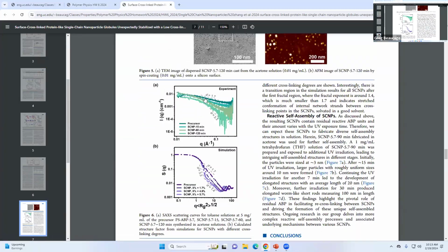So he shows this weak slope. The intensity is kind of proportional to the mass, and this is 1 over the size. You have a fractal law: the mass goes with the size to the fractal dimension. So if it's a rod, it'll be to 1. If it's this random walk, it's to the 5/3.